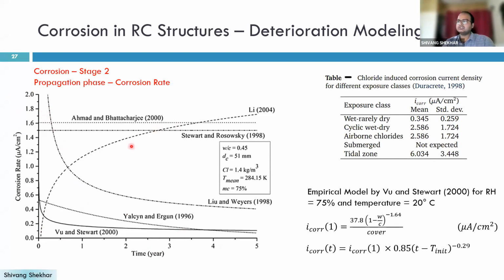Some say it's constant, some say it degrades with time, some say it increases with time. But the most widely used in the literature is the Vu and Stewart model. That gives you the initiation corrosion rate, and then it says that it decreases with time.